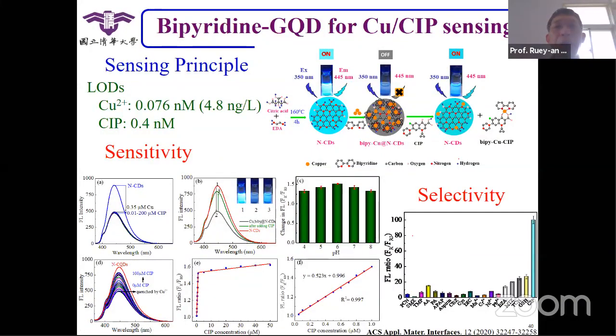We can still use these carbon dots or graphene quantum dots to detect copper, or to detect some antibiotics like CIP. When you use the graphene quantum dots to detect copper, the detection limit is around 4.8 ng/L. This value is actually more sensitive than AAS and very close to ICP-OES, so that is quite good. We can also use this to detect CIP, an antibiotic used for our food, and the sensitivity is also good. All this shows that graphene quantum dots can do a lot of things.